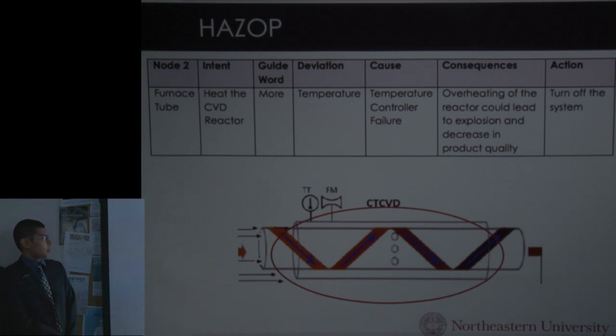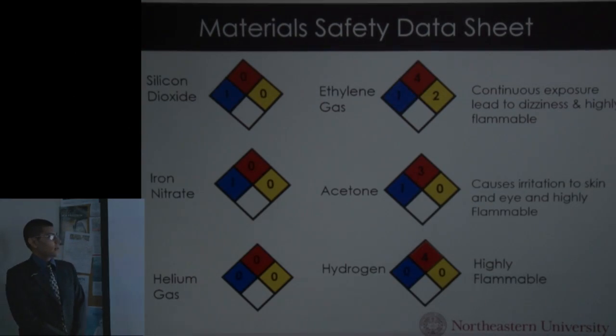The next node is the tube furnace. Like I mentioned before, there are various ranges of temperatures possible in the tube furnace. Especially we're dealing with flammable gases such as hydrogen and ethylene going into the furnace. Improper temperature range can cause flames to occur in the tube furnace. And in order to avoid such possible scenarios, it's better to have an emergency turn-off system in case the temperature exceeds the limit.